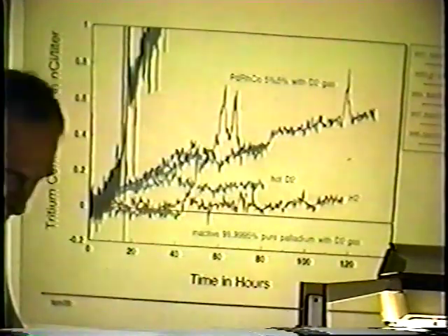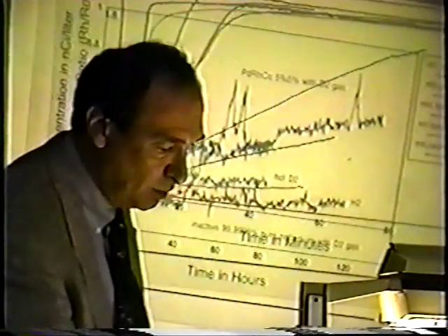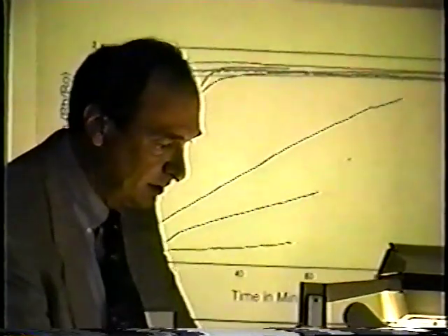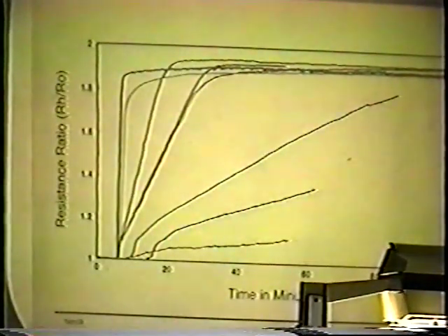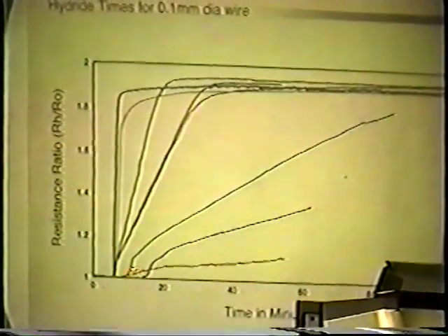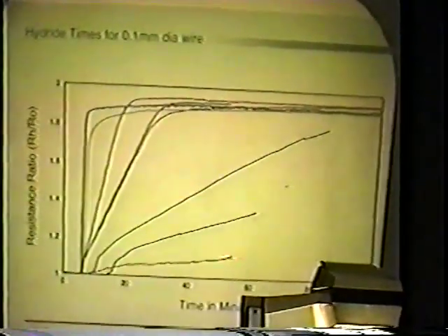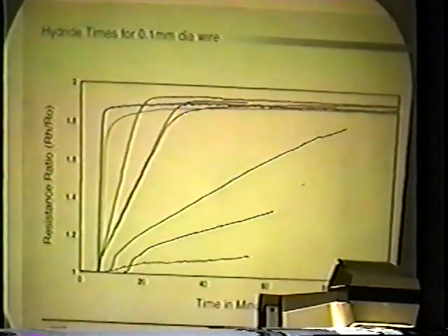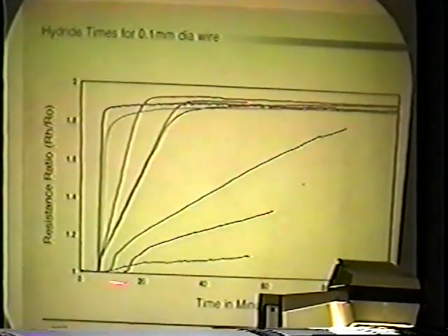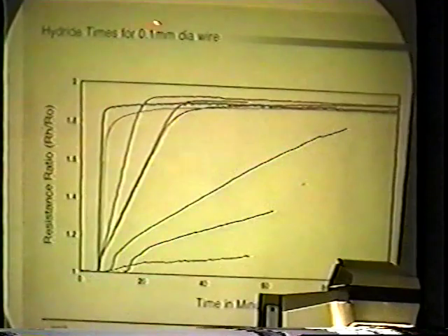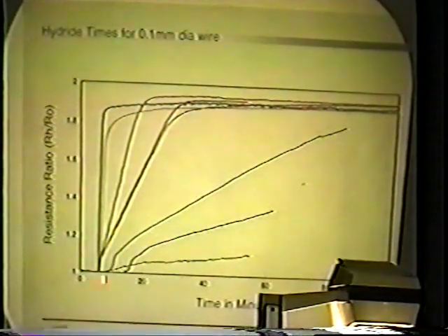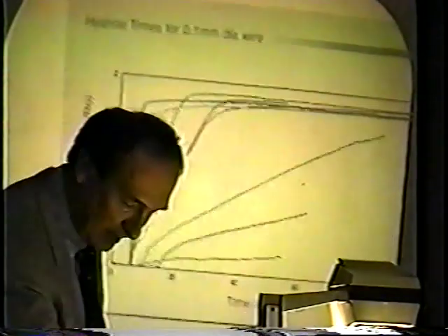Basically what we did was we spent about a week to get this sort of condition on a palladium wire. So these are times, and this is the resistance ratio of a 10 centimeter palladium wire. We put it in the loop right after we've run one of these cells and flushed it, and you won't have any hydriding in this wire. As you clean the loop, you're coming up to this point where this is a 2-minute hydride for this 0.1 millimeter in diameter wire, and that is pretty much theoretical diffusion rate. So that's when we ran the last one.